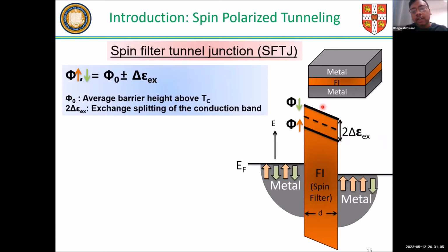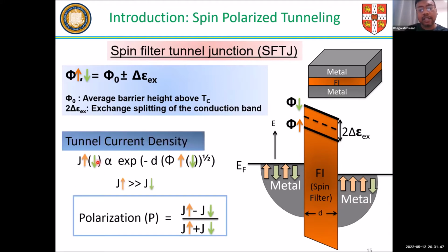So how it works is that you have a ferromagnetic system where there is a spin split at the Fermi level. If you have an insulator or semiconductor, you have both valence band and conduction band, and they have exchange splitting. If the conduction band has exchange splitting, then the barrier heights will differ when you take this system as a tunnel junction. For a tunnel junction, what is important? The barrier height and the thickness of the barrier. So if you assume that your barriers for the two different spin directions of the electron are not the same, then, as we know, the current density depends exponentially upon the barrier height.